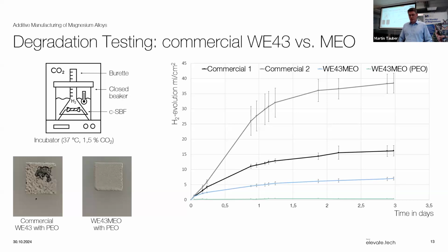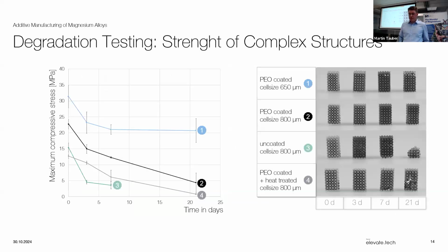And looking at this small test, which was only covering, in this case, 3 days, we already see that commercial alloys, which are on the top, are corroding quite fast. And these are all 3D printed samples, by the way, bulk material. If we take commercial powder, they corrode quite fast. If we take our WE43 Meo, because it's really, really clean, it already corrodes way slower because, for example, we don't have any iron in it. And if we then do the PEO surface conversion, you can see that it's almost not visible in the first days. So the corrosion slowed down quite a lot, and this benefits the material.